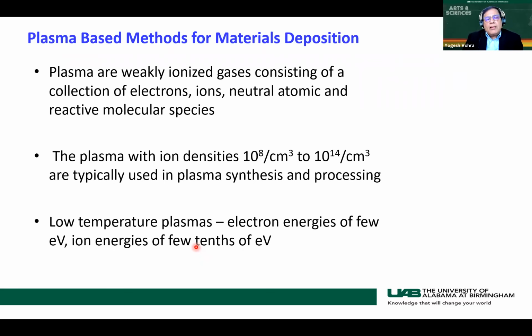So, plasma-based methods for material deposition. Just recall that plasmas are weakly ionized gases consisting of a collection of electrons, ions, neutral atomic and reactive molecular species. One of the key parts of my talk is also going to be about reactive molecular species present in plasma, which allow for new growth chemistry. The plasmas we'll be employing typically have ion densities from 10^8 to 10^14 per cubic centimeter. Keep in mind that these are low temperature plasmas where electron energies are a few eV, typically half an electron volt or 1 electron volt, and ion energies are a few tenths of an eV.